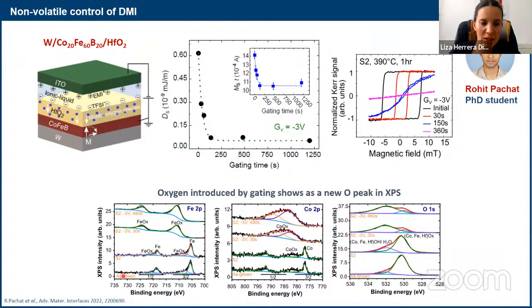Here, you can see the first two spectra that I showed you before and after annealing, but then after voltage, you can quickly see how the metallic iron disappears and transforms into oxide, same for cobalt. And what I said before, the increase of this peak in the oxygen spectra can be related to, of course, the oxidation of the metals, the oxygen in the oxide, but also to OH in the system. So we can really see that we are pumping oxygen into the system.